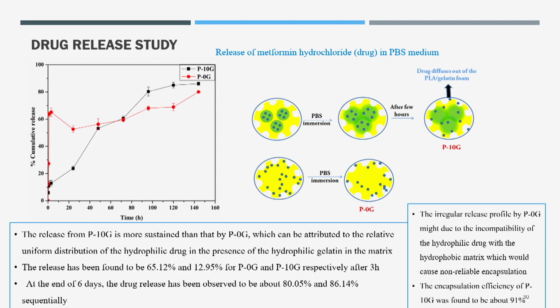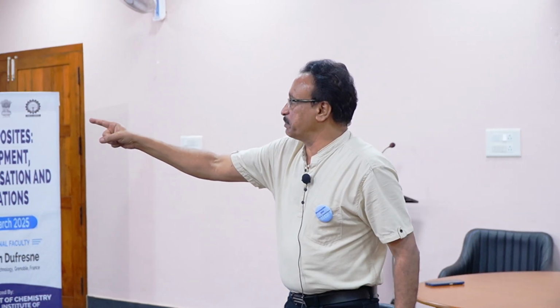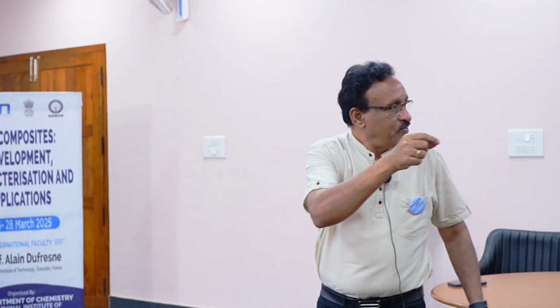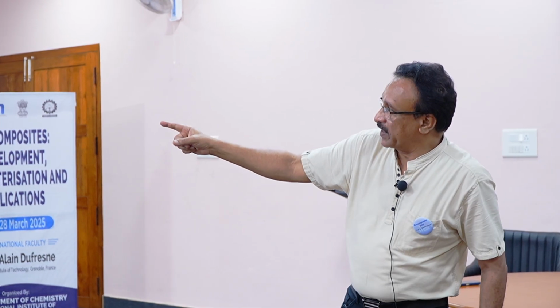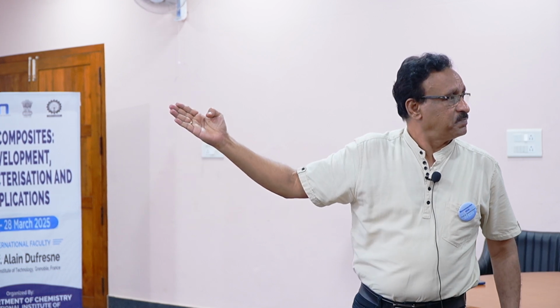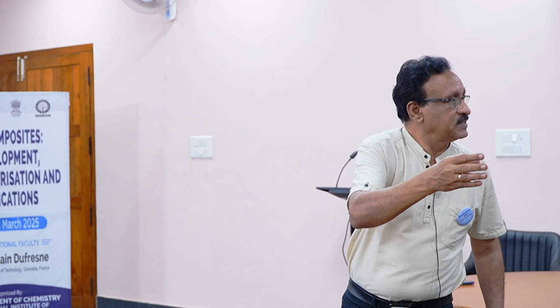And this is the drug release examination. It's a comparison between simple PLA and gelatin modified PLA. Simple PLA is the red graph. P10 has been identified as the best system. The black graph is gelatin modified PLA. She has loaded a drug, metformin hydrochloride, into that, and at a specific pH value she is measuring how much of the drug is coming out. If you look at the red graph, suddenly the graph goes up to some quantity. The moment you start release, the drug will come out, from PLA alone. Then slowly you can look at the red graph.